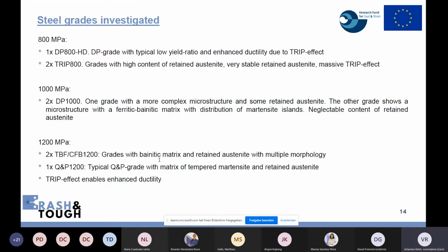In the strength class 1000 megapascal, we had 2 DP grades, 1 grade with a more complex microstructure and some retained austenite, and the other grade has a microstructure consisting of ferritic bainitic matrix with martensite islands. This grade had a negligible content of retained austenite.